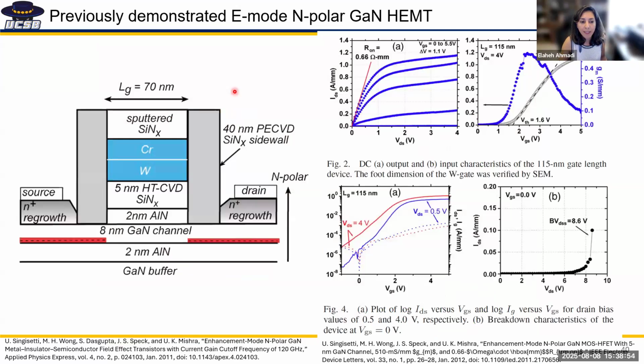On nitrogen polar specifically, there is this work that was done by Uttam and Manho in Umesh's group, where basically they had a 2 nanometer aluminum nitride on it, and using a self-aligned process, they removed the aluminum nitride everywhere and kept it only under the gate to show the E-mode performance. And they got very nice E-mode behavior with a high threshold of 1.6 volt. But there were no power measurements published on these devices.